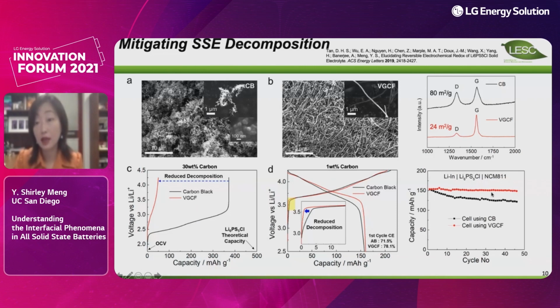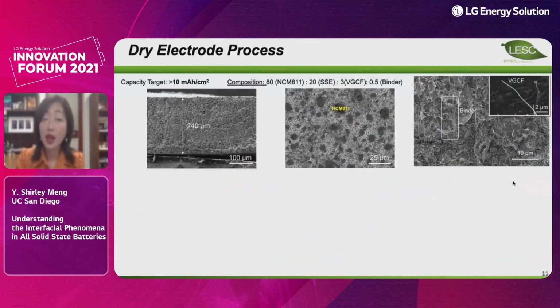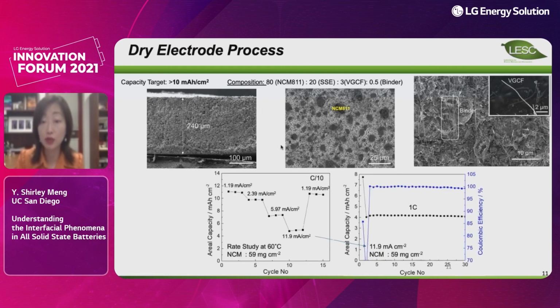Of course, this NMC811 is protected with a borax coating. But the effective current density, the critical current density, still remains low, though we did solve this cathode interface problem. In the more recent program we are doing, we have successfully managed to make cathode electrodes through dry electrode processing that obtain more than 10 milliamp hour per centimeter square loading. Using these vapor growth carbon fibers and special binders, we can achieve very good utilization of the cathode materials.